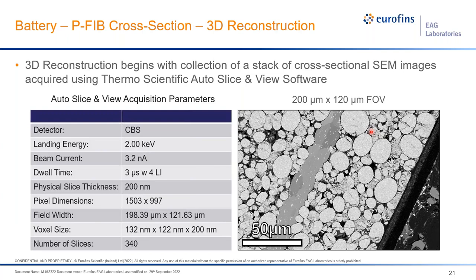So in certain cases, we'd be interested in actually creating reconstructions of this entire complex structure. And so in this case, we're going to collect a series of images from a region of the sample here, approximately 200 microns by 120 micron field of view. We're going to take 340 slices, which essentially gives us about 200 nanometers per slice. And then we're going to take all these slices and utilize Thermo Scientific's reconstruction software to create a three-dimensional